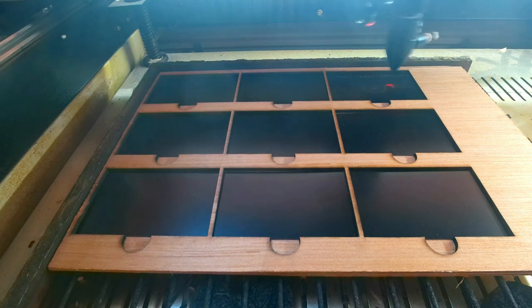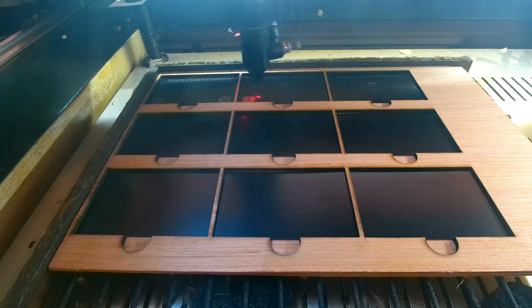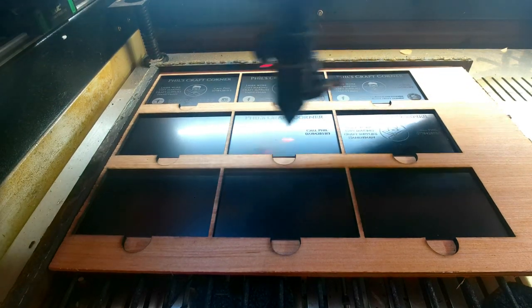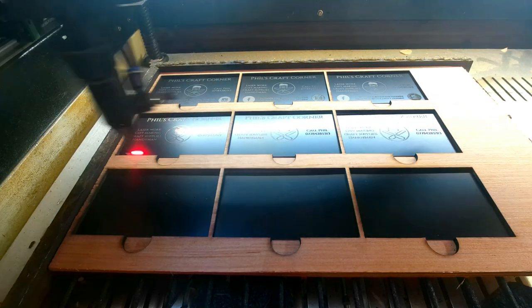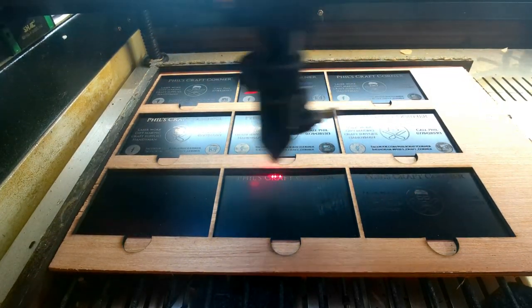We're over the laser now — I've sped this up to save time. As you can see it engraves really nicely on there. This is at 300 millimeters a second at 18% power on my 50 watt Chinese laser and you just get really crisp lines. What you will find is some of the engraving will have little dust from the anodized being vaporized, but at the end you just wipe it off with a damp cloth. I use wet wipes which I keep handy and that makes the process a lot easier.